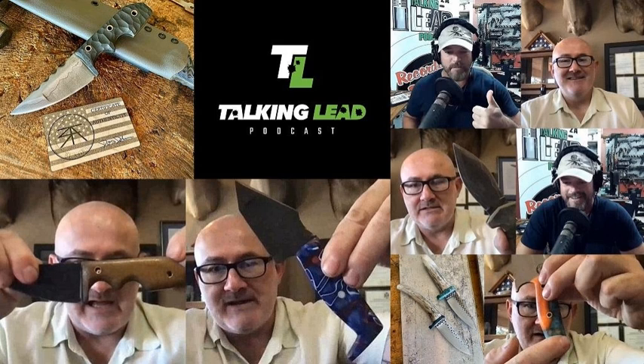What's the best steel for a beginner to start out with? The best steel is probably 1084, which is just a standard high carbon steel. It has about 0.8-plus percent carbon in it, and it's good because it's less money, and you heat it up to about 1475 degrees, give or take, and it doesn't require a soak time. If you just have a propane forge, you can heat it up to about 1475, maybe 1500 degrees, and then instantly quench it. It doesn't have to sit at that temperature for 10 minutes. 1095 has to sit for about 10 minutes at temperature to be heat treated properly. So 1084 is probably the best.